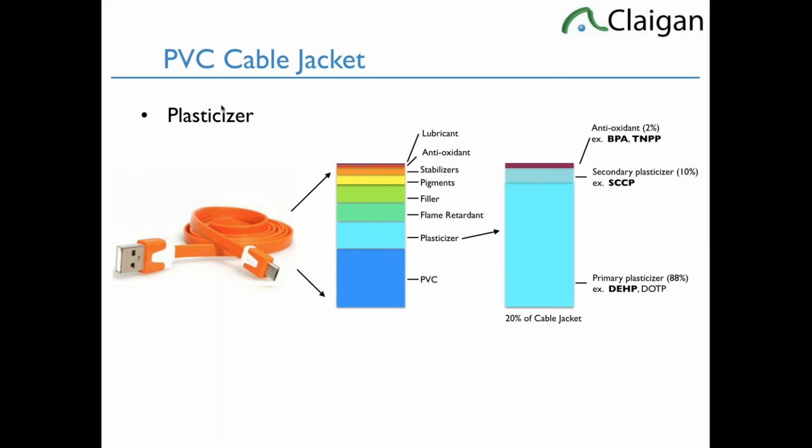However, the orthophthalate chlorinated paraffin 52 blend. Chlorinated paraffin 52 is chlorinated paraffins controlled to 52% chlorine. In theory, on average, they're medium-chain chlorinated paraffins, which aren't regulated yet. However, it's on average. They only control the chlorinated paraffins by chlorine content. So about 20% of MCCPs, medium-chain chlorinated paraffins, are actually short chain, which are banned in Europe and Canada. So because of this, the CP52 and DHP blend ends up being about $600 and some a ton, which is about half the price of DHP alone.